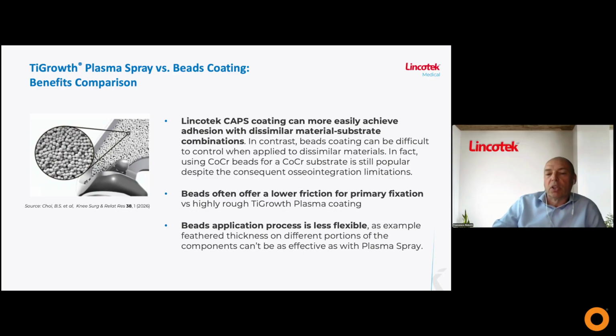Also, bead coatings offer lower friction for primary fixation, compared with the highly rough TiGrowth coatings. And bead applications are also less flexible. For example, if you need a feathered thickness in different portions of the components, this is really hard to get with bead coating, whereas it is really possible with the plasma spray technologies.